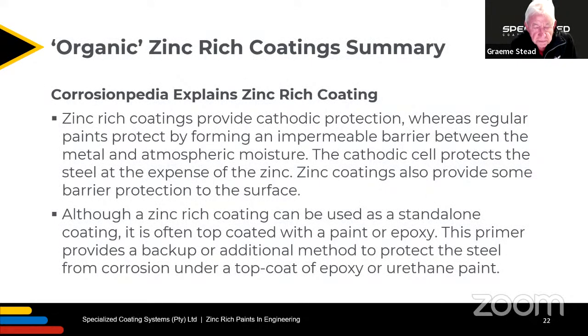Zinc-rich coatings provide cathodic protection, whereas regular paints protect by forming an impermeable barrier between the metal and the atmospheric moisture. The cathodic cell protects the steel at the expense of the zinc. Zinc coatings also provide some barrier protection to the surface.